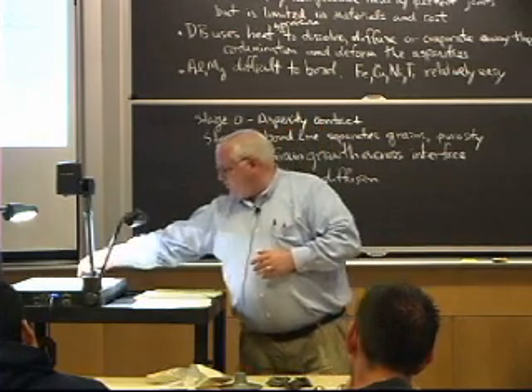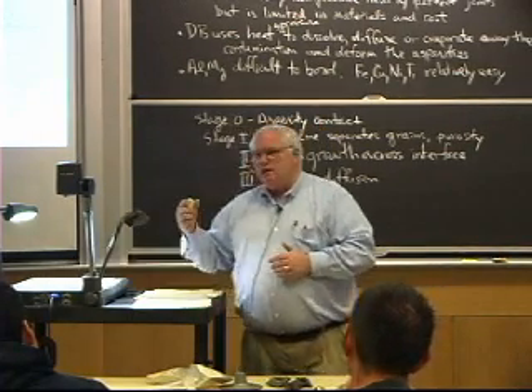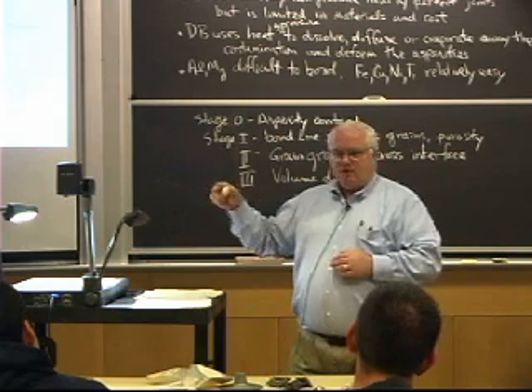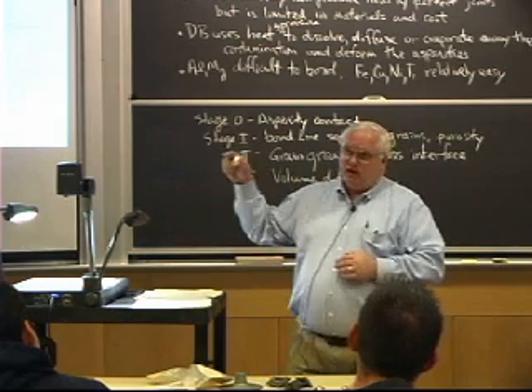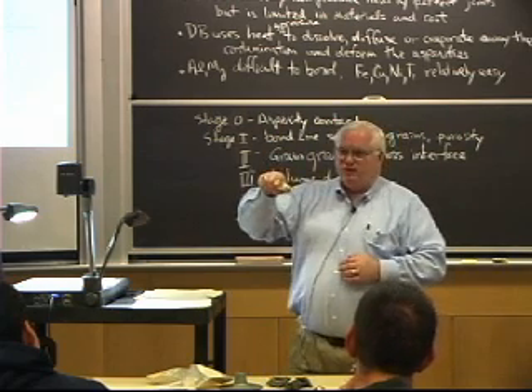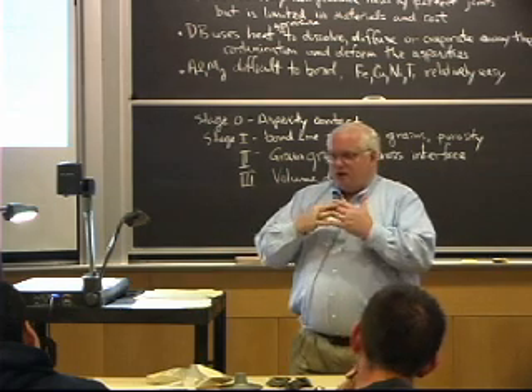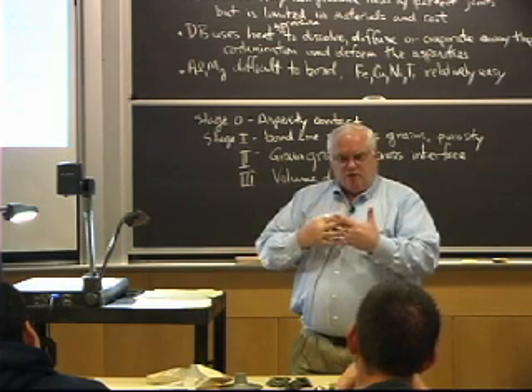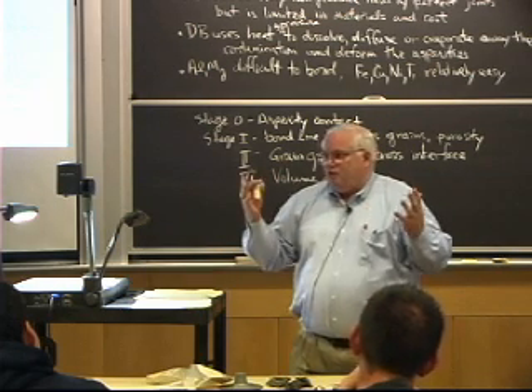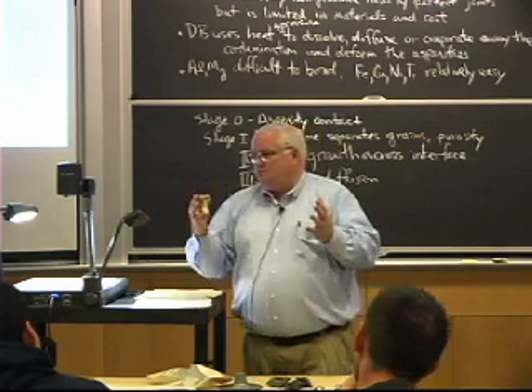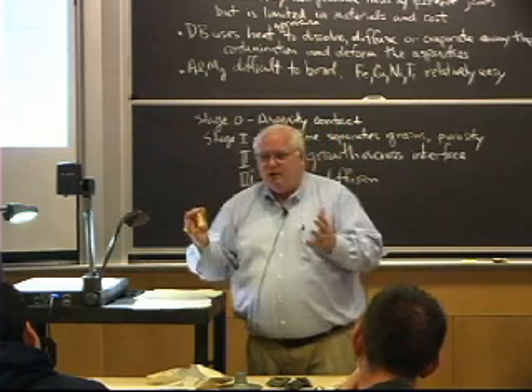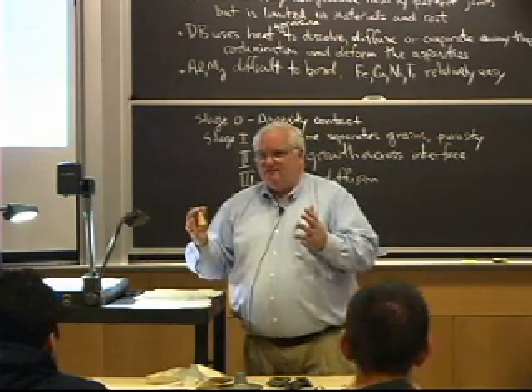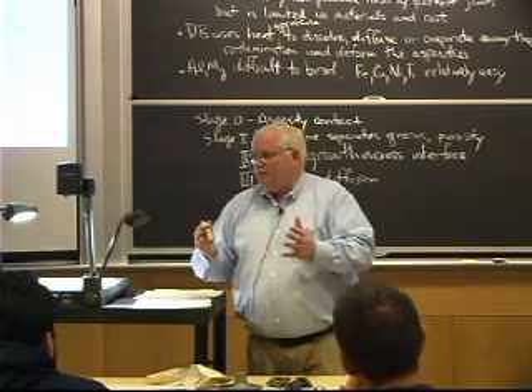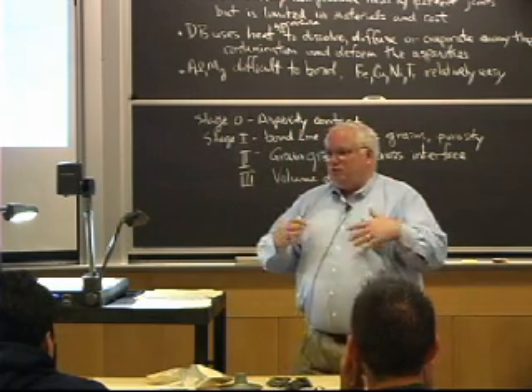But if I have volume diffusion, I've got to move those atoms all the way from the inside of that grain boundary, all the way out inside of that grain, all the way to the surface of the grain, in order for the grain boundary to rearrange and annihilate the vacancy. I can't get rid of a vacancy on a crystal lattice. I can move it around, but I can't eliminate it. Okay? There's nowhere for it to go. It has to get to the edge before it can be eliminated.